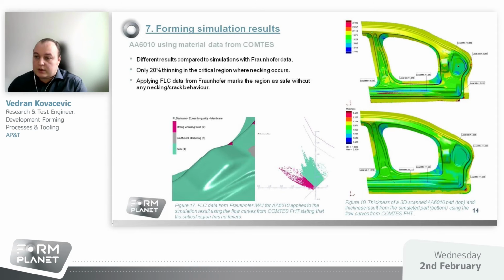Moving on to the tests using the material data from COMTES, we can see that they display a different result. It may seem that this card has an improved performance as the deviation from the nominal 2 millimeter thickness is better than for the result using the material data from Fraunhofer. But this is in fact misleading because there is considerable thinning in reality in the regions that were marked red in the previous picture, especially where the strong necking occurs. In the simulation using the COMTES card, there is only a thinning of 20%, which is incorrect. Moreover, applying the FLC data from Fraunhofer to the simulation shows that this region is marked as safe, further indicating that the material card has reservations in terms of accuracy.